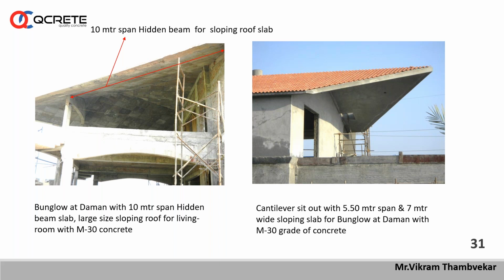At site, what happens? People just sprinkle water for a certain time and then leave it as it is. Whereas the cubes we put in water for 24 hours. So there is always a difference between the cube strength and the strength available at the site, or the strength of material provided for beams, columns and slabs. So to get good strength of concrete in RCC members or RCC frame, following a good practice of continuous curing is very important. Curing is also very important, because even though there is another method of applying a curing compound, it's not possible to provide a curing compound for all structures.